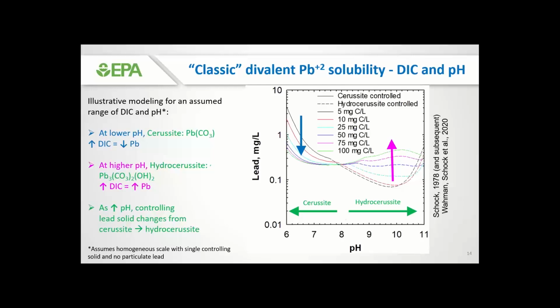The y-axis here is lead solubility in milligrams per liter. So we really want to have the lowest possible lead here on the y-axis that we can for our conditions. But for lower pHs on the graph, increasing the DIC drops lead, which is good. So we would like to have higher DICs at lower pH, but at higher pH, which is the right side of the graph here, increasing the DIC actually increases lead concentration.